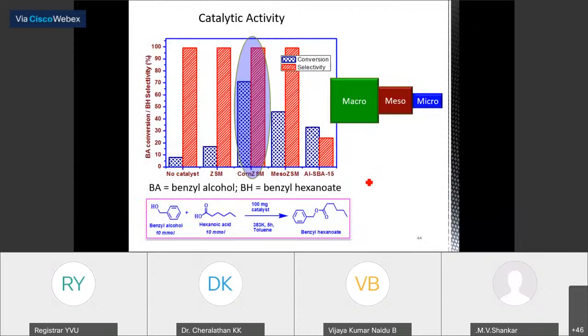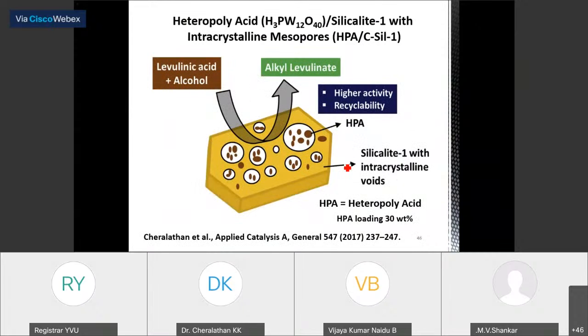We did a simple reaction involving bulky reactants and products. We found that this catalyst, which is having macro, meso, and micro porosity, is performing better even than this mesoporous catalyst. Because of the presence of the combination of all these three types of porosity, it is showing better activity. Not only that, we have also prepared a zeolite which is having this kind of mesopores and then loaded heteropolyacid. So nanoparticles of heteropolyacid loaded into this silicalite-1, which is a non-acidic zeolite.